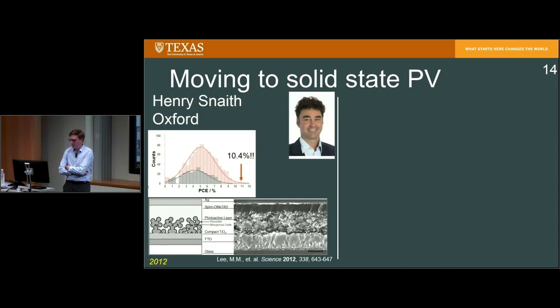However, the very first people to try got really cool results. Henry Snaith at the University of Oxford, though it did take him 300 to 400 tries, managed to get a solar cell with 10% efficiency using the solid-state hole transport material spiro-OMeTAD that you can see here. This was wild because this was a time when there were almost no solution processed PV that got up to 10%. And here was the third paper in this field getting to 10% in a fairly benign trial.